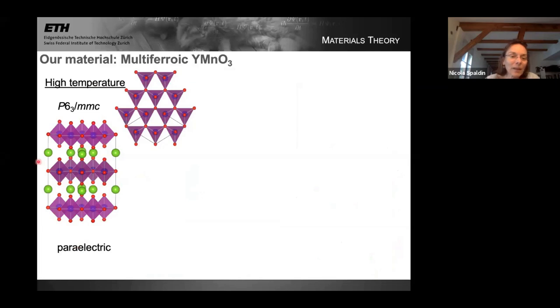So at high temperature, the yttrium ions are forming perfect layers, as are the manganese ions, the purple ions in the middle of these polyhedra. Surrounding the manganese are oxygens, shown in red. To see the connection between the manganese, we have to go up here and look from the top. Here the manganese is the large purple ion surrounded by three oxygens in the plane, and there's an oxygen above the plane and another one behind that you can't see.